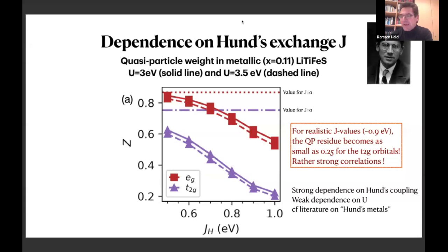Very nice topic. So I wonder about the Hund's exchange. You said it's 0.9. Sometimes you have something like 0.9 or 1 if you have a density kind of Hund's exchange, but it's somewhat lower, 10 or 20% if you take the full SU(2) symmetry into account, because the singlet and triplet splitting is larger in the SU(2) form. So is this 0.9 including this effect, or is it the RPA value from a density kind of DFT calculation?